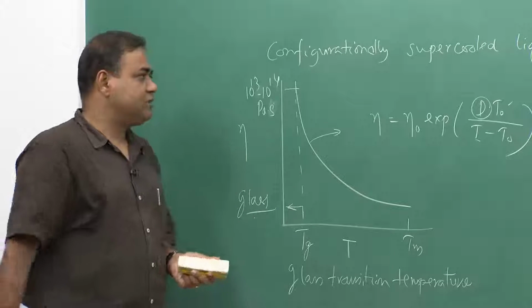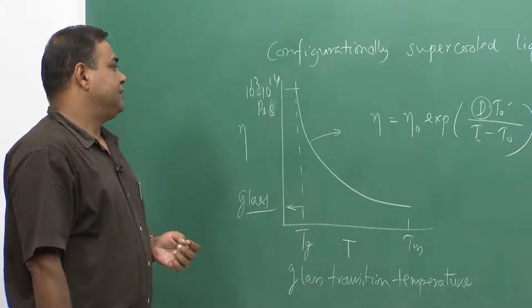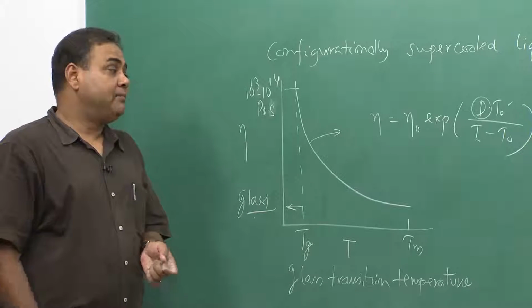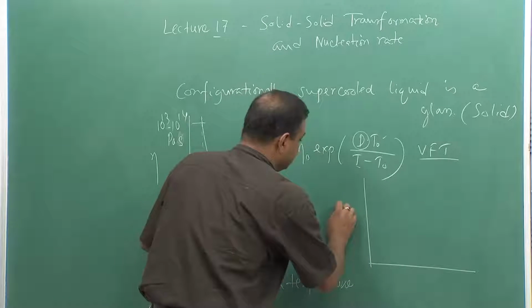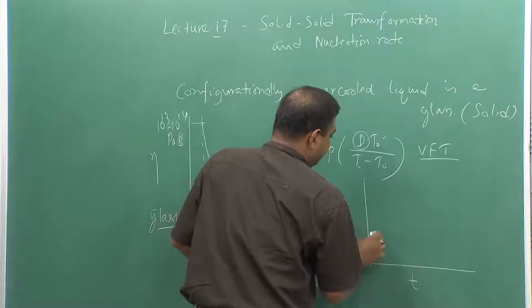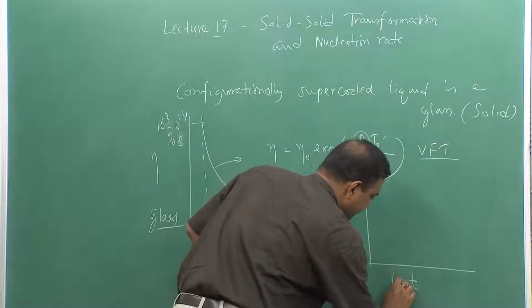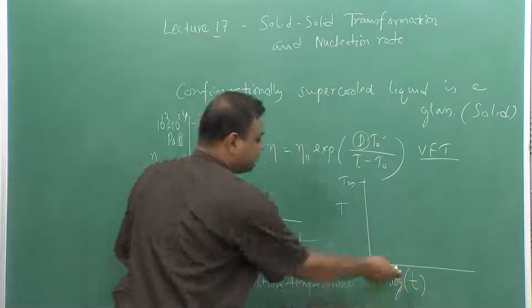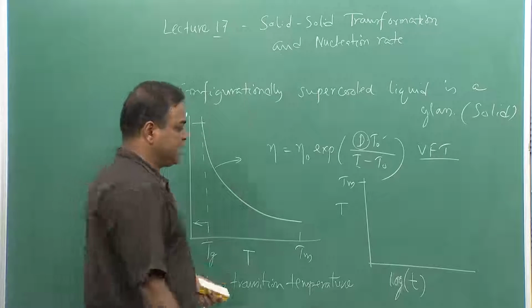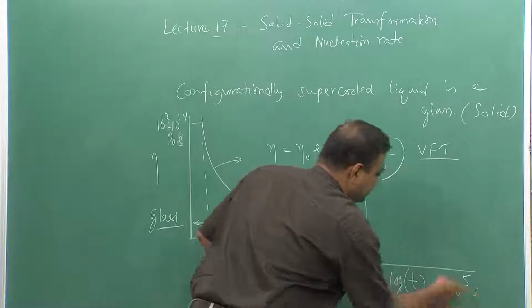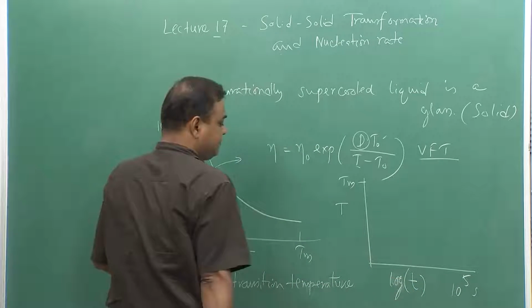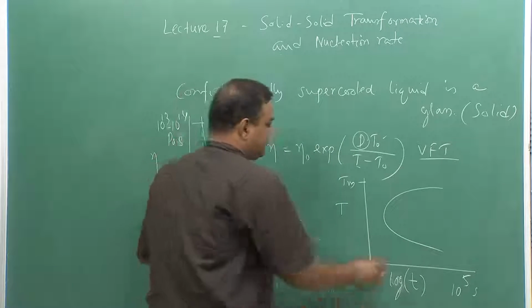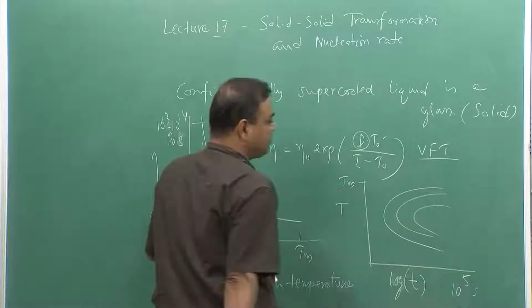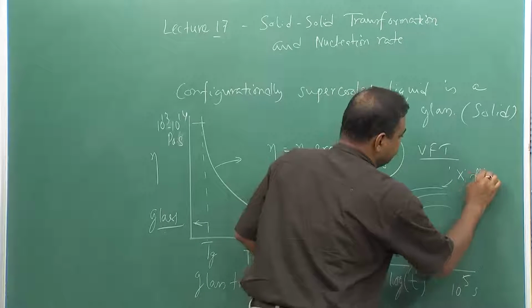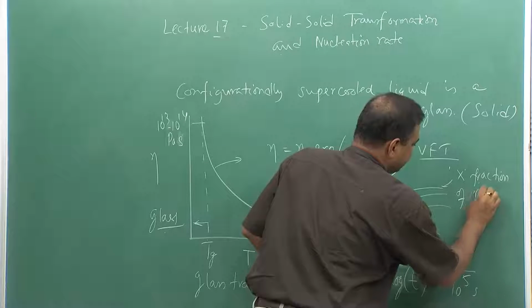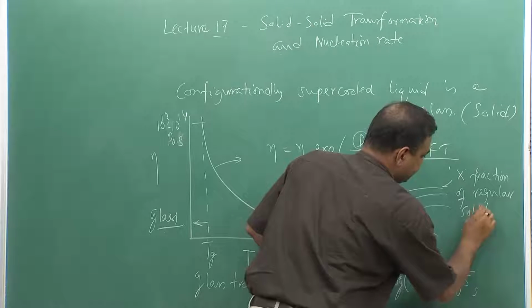So this is a kind of situation where we do experience glassy alloys, and at that time the solid-solid transformation is a critical issue, and we can also construct a TTT diagram for solid-solid transformation. If this is Tm, generally we consider this axis in the form of log, because this time can become a large value, so it can reach 10 to the power 5 seconds. So in order to put it on the same axis, we take the time as log. So then the graph becomes like this. This is also a C curve, and these particular lines are indicating the fraction of transformation, which is regular solid formation.